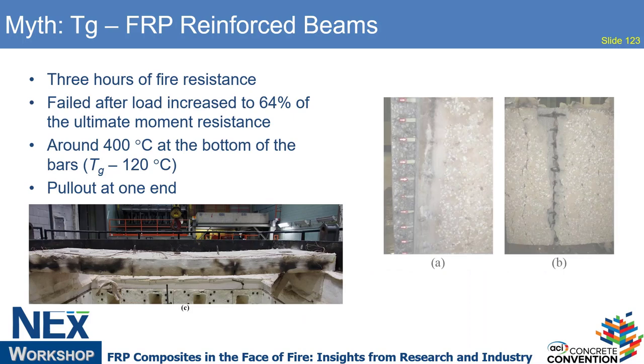So a little bit about the FRP reinforced concrete beams. This is similar to what Steve pointed out in his presentation. We had 3 hours of fire resistance, and about 400 degrees centigrade at the bottom of the bars, measured at the center in these tests. That's roughly 800 degrees Fahrenheit, whereas the glass transition temperature was only 120 degrees centigrade, a little over 250 Fahrenheit. So obviously you don't get failure.